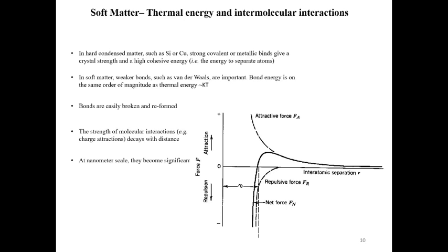But the advantage of such a weak bond is that any small perturbation, or the thermal fluctuation that you provide in the system, can easily break or rebond those two particles. That is the magic of the soft material, that they can assemble into a certain pattern. And meanwhile, you can use either thermal or external field, a relatively lower amount of energy, to easily break those bonds and reconfigure them into another pattern, which is not available for metal material.